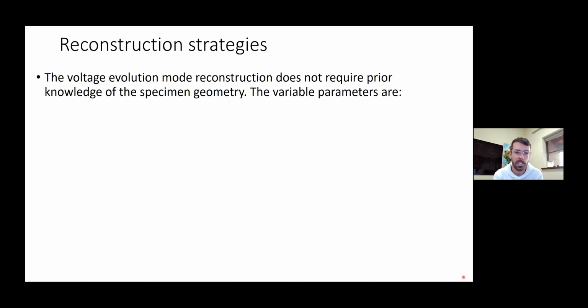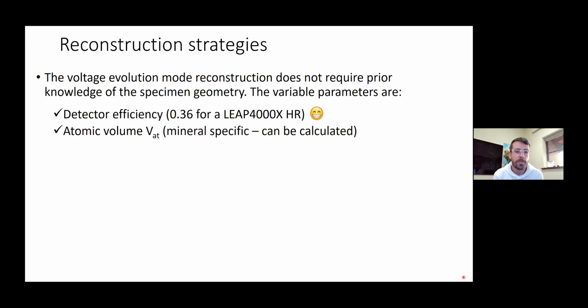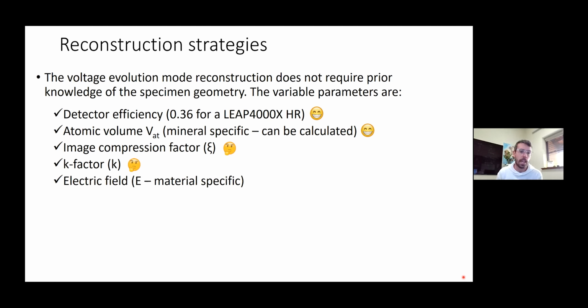So if we think about the voltage reconstruction, in that case we don't need to know prior to the reconstruction the exact shape of our specimen, and there are variables in the equation. The detector efficiency, which we know relatively well depending on which instrument we use. There's also the atomic volume, which is mineral specific; we can calculate that, so that's easy. Then we have the image compression factor, Xi, where we don't have the crystallographic planes to actually measure it from our data, but something we don't really have an idea of. Is also the K factor, which can sometimes vary, and finally the electric fields, which should be material specific.